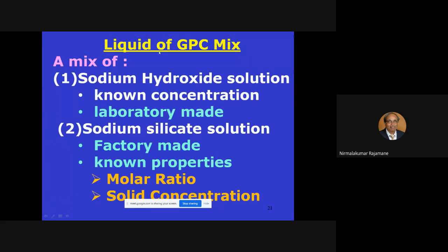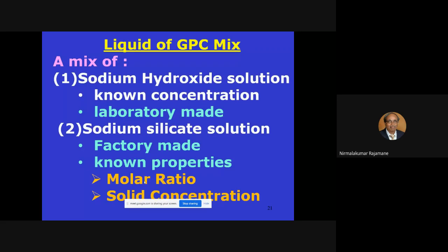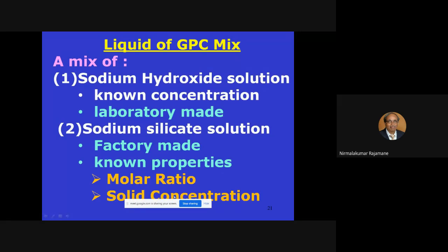The liquid component of geopolymer is a mix of sodium hydroxide solution and commercial sodium silicate solution of known properties. The key property is the molar ratio — the ratio of SiO₂ to Na₂O. Sodium silicate does not mean equal proportions of Na₂O and SiO₂ — the ratio varies widely. We also need to know the solid concentration and sodium concentration. Many Indian publications do not report these properly.